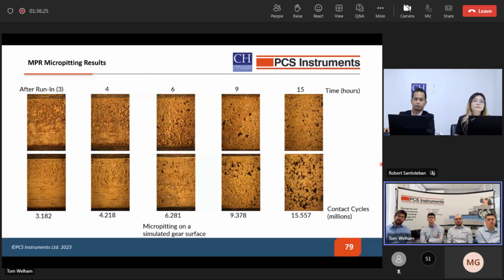Now, another great thing about the MPR is you can stop the test, pause it, and you can take the roller specimen out. You can measure the level of micropitting by looking at the profile, measuring the track width, and you can see how the profile width increases throughout the test, so that we're seeing a measure of the level of micropitting throughout the test. So we have two oils here, and both oils are generating a significant amount of micropitting. The track width throughout the test is increasing. So we're seeing more and more micropitting resulting in radius loss of the roller specimen throughout the test.